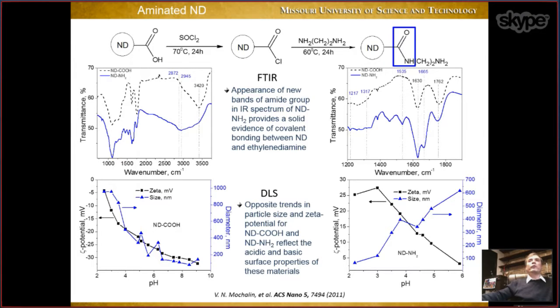Now to prove that we really form this covalent bond here, we use IR spectroscopy. And first of all, of course, we see signals typical for CH vibrations because we have two CH2 groups here attached to nanodiamond, right? So we see CH stretch vibrations here of higher intensity compared to the initial material, but it's not a convincing proof because, well, if you simply physisorb this diamine on the surface of nanodiamond, you will still see these signals from CH groups.